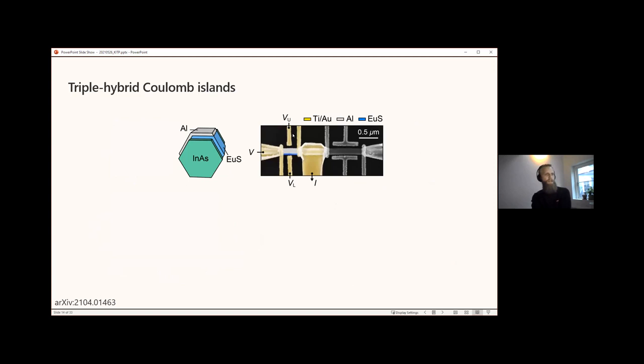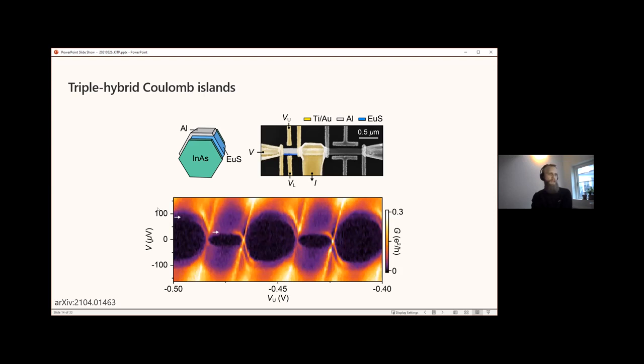And those are the Coulomb blockade in the islands made on the same wires. And in this case, we take the identical wire and fabricate two Coulomb islands next to it, but measure only one at a time. Similar to the previous device, it has upper and lower gate voltage, but now again, two cutter barriers at either end that allow us to tune this island into a Coulomb blockaded regime. And when we do so and measure the conductance of the device as a function of source drain voltage and upper gate, which is located on the aluminum side, we find the following Coulomb blockade pattern with sequential tunneling lines.